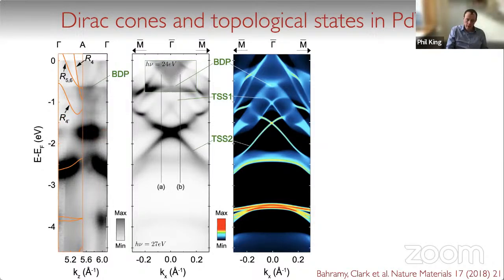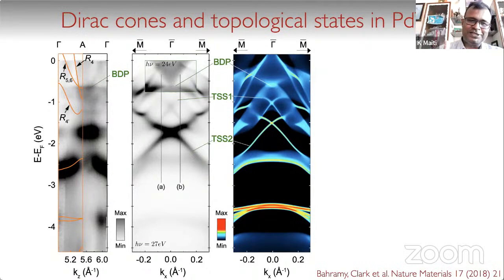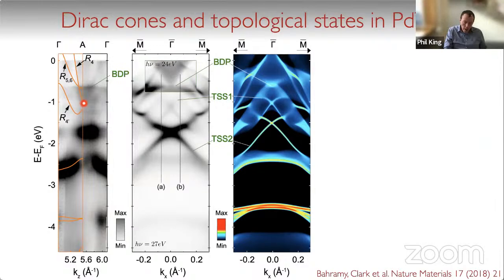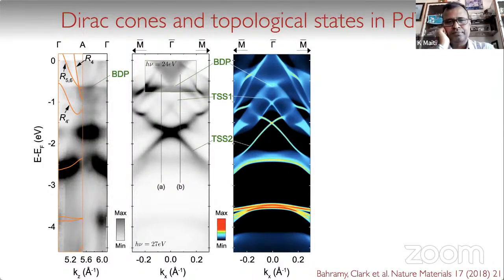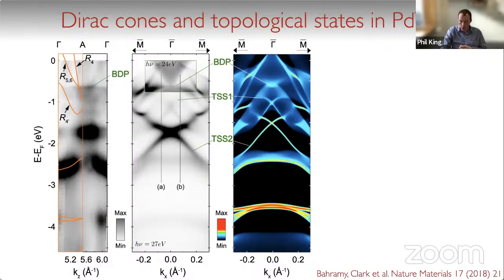So there are no bulk states anywhere in here, and so this is rather clear, and it's clear in the experiment as well. The intensity variation is because of some matrix element, well, not really matrix element, I would say, but the one up here is a surface resonance. So here there are kz-projected bulk states, and so it's still a surface state, but the wave function is more extended into deeper layers below the bulk, so it's more spread out, and then it shows up a bit weaker in the experiment, and you see a similar thing in the supercell calculations. There's just less wave function weight in the first layer.